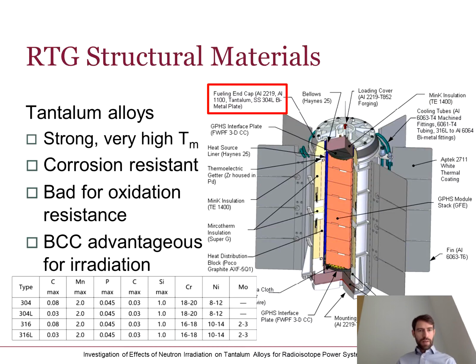Then we come closer to my patch, as I spend a lot of my work on BCC based materials. If we wanted to go higher in temperature, we would really max out. We wouldn't be able to use stainless steels, or potentially even the nickel alloys, if we went to very high temperature reactors. Another advantage of the BCC elements, particularly refractory metals, for example tantalum, is the irradiation damage tolerance. In terms of damage tolerance, irradiation-induced defects and irradiation-induced helium, nickel and cobalt don't do well in this regard. So in terms of irradiation damage, BCC is generally advantageous.